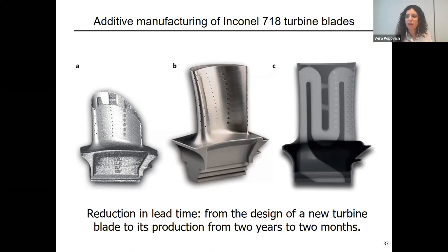In figure A, you can see the as-built turbine. There it already shows you a very clear limitation of this technique. And the limitation, as you probably could already guess, is the surface inhomogeneities, the surface roughness of the finished product. If you optimize the process, it can be about 20 microns. You can go lower with certain remelting technologies. But this is your limitation, and this for sure could matter, especially for dynamic applications such as fatigue, where you have initiation of fatigue cracks at the surface.